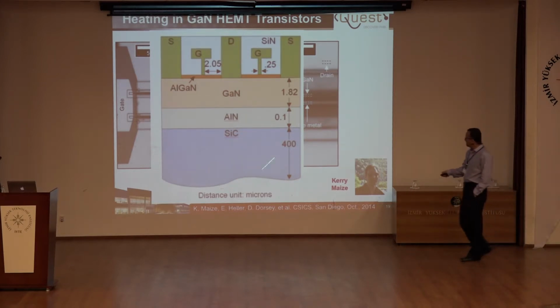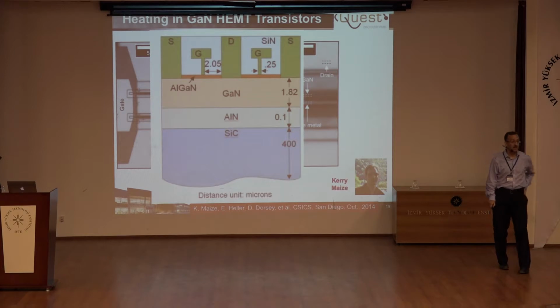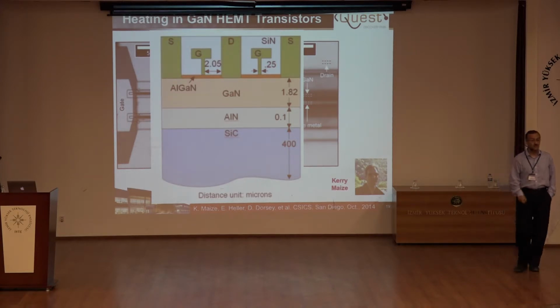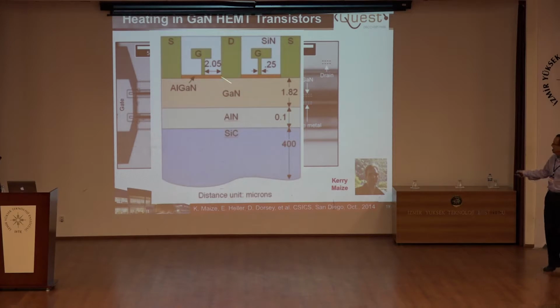I have a substrate. These are thicknesses in microns. In the top microns, I put some materials, and then there is a source and a drain and a gate. Typically, the gate is a quarter of a micron, very small. That's where the nano comes in. And I control the current from source to the drain by changing the gate voltage. What happens is that in the transport there is some dissipation. It heats up, and that heating is what we need to minimize, and that's what makes the device perform less well. Two effects about heating are important.